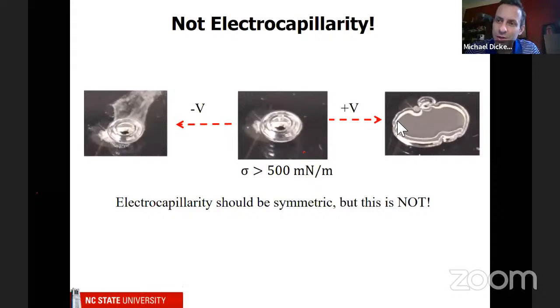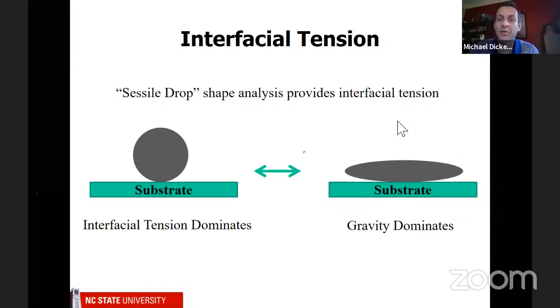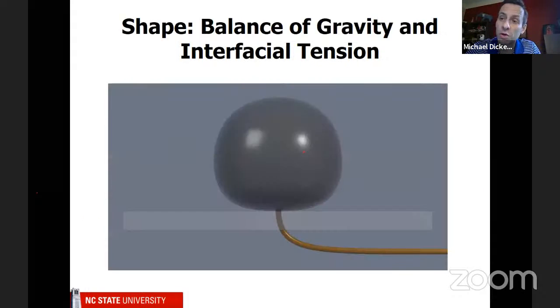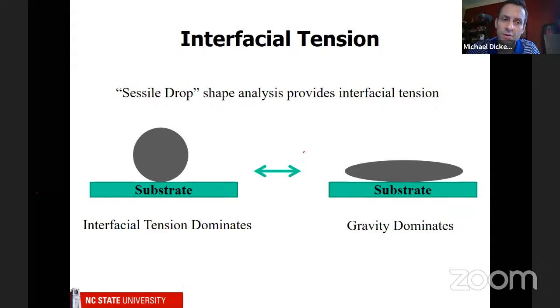Okay, so what do we do? Well, we go to the lab and we try to measure something. The thing we try to measure is the actual surface tension. We call it interfacial tension because it's in contact with another liquid. But anyway, the way we do this is very simple. We look at the shape of a droplet, called a sessile droplet. It's just a droplet resting on a surface. We assume there are two forces: surface tension, which wants this to be a sphere, and gravity, which wants it to be flat. Depending on the shape, you can figure out the surface tension.